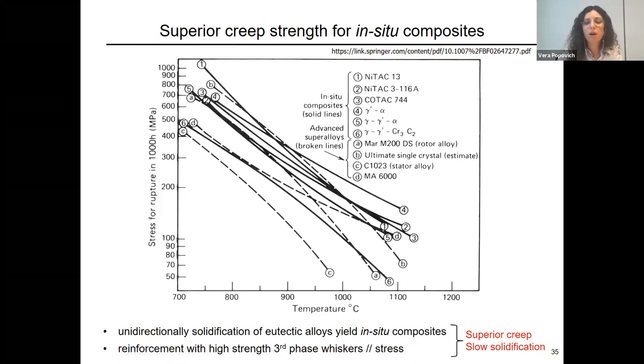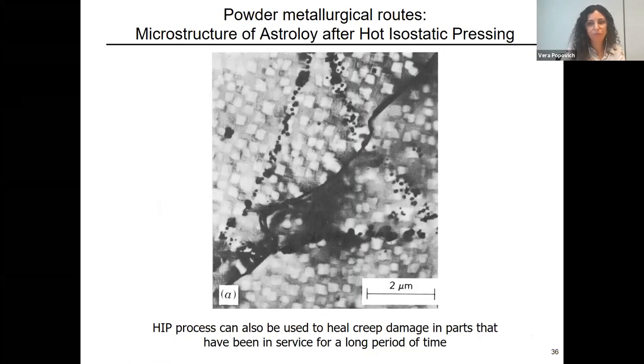They normally are reinforced by high strength fibres or whiskers parallel to the applied stress, but this comes at a cost. They do have superior creep strengths, but they require a really slow solidification rate and a really high cost in terms of time involved. You can find more details about these alloys and composites in the link here on the side. But as I said, it comes at a really high cost, and it's no wonder that they are not commonly used for normal aircraft engines, for example.